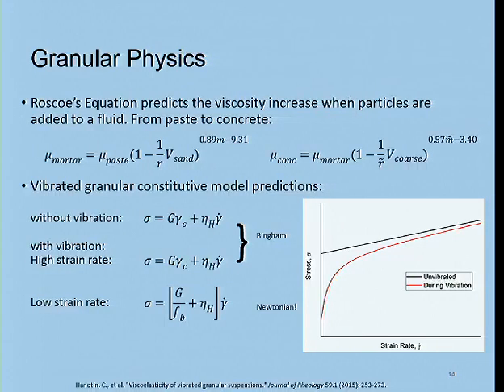So it was very interesting to see if this would help us explain the behaviors that we were seeing. And so we've got these models, one of which is called the Roscoe's equation, and it gives us the ability to put in volumetric presence of sand and aggregate and so forth. And we can use the same kind of model to put in coarse aggregate for the concrete and so forth. And it gives us essentially the right type of model, the right kind of constitutive performance that we were looking for. So this was always encouraging and led us to move on and see that the granularity of concrete was a very big part of the behavior we were observing.